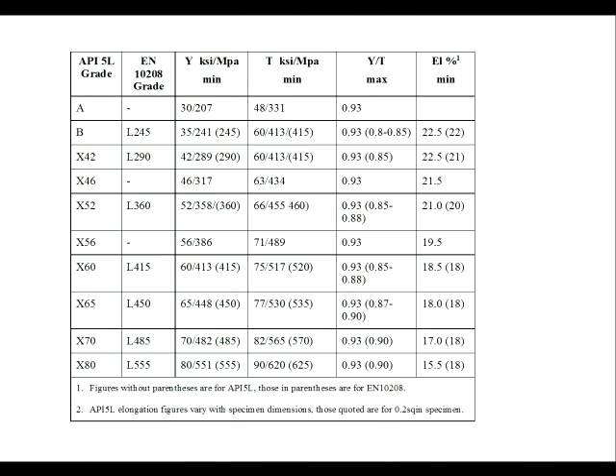The elongation should all be about 20%. And as we go up in strength, the material becomes more brittle and that elongation number comes down. And one of the reasons, therefore, that we were worried about going to these higher strength grades is that their susceptibility to fracture and their toughness becomes more of an issue. And that's why that's another thing that's specified.